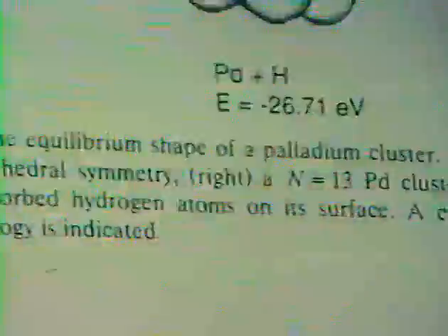And Professor Mossell tells me that he has been unable to make catalyst particles smaller than 20 angstroms that retain some kind of a regular shape. He says above 20 angstroms that they do get regular shapes, and he is able to get some reproducible results on these that correspond with regular shapes. But below that, he doesn't, and so he